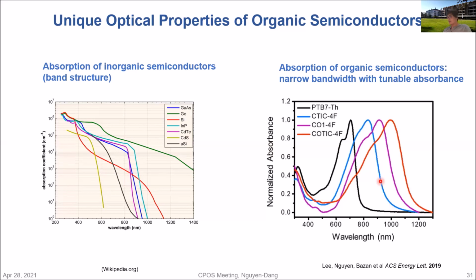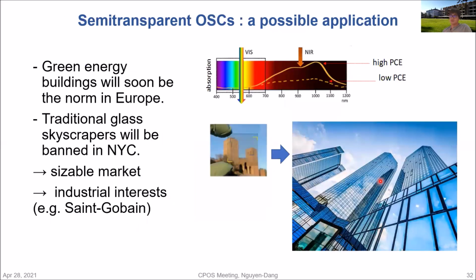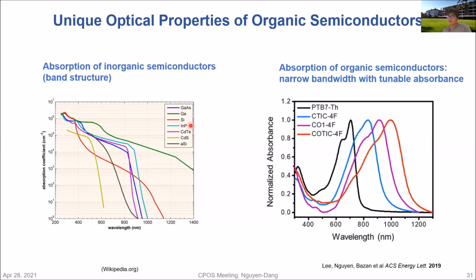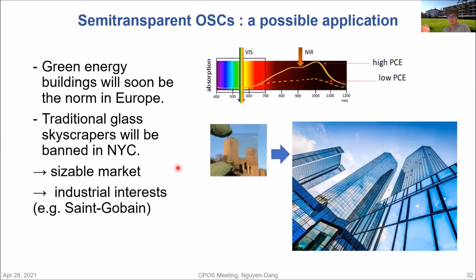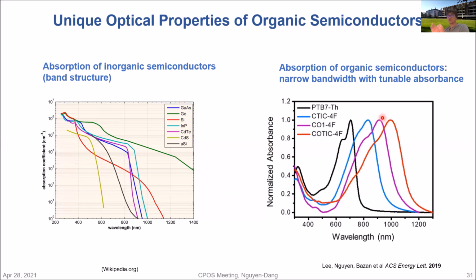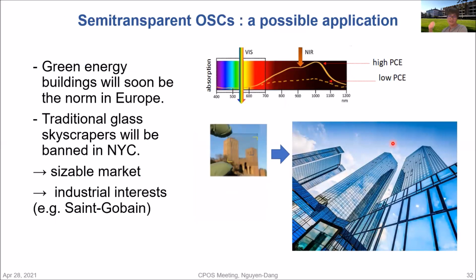So that is fascinating, because we have to find applications. For semi-transparent organic solar cells, if you have inorganic semiconductor, you cannot do anything other than reduce the thickness of the film. Whereas with organic semiconductors, you can tune the absorption at the very specific wavelength that you want. And if we can apply the metasurfaces, we can enhance it even higher. So we can harvest higher energy in the infrared and let the visible go through. And semi-transparent organic solar cells are a big market right now, because basically green energy buildings will be the norm everywhere.